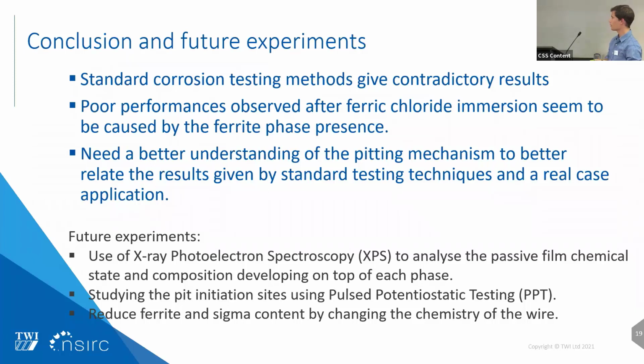So as for future experiments, we'll run some X-ray photoelectron spectroscopy to characterize the passive film that we have on top of each phase. The goal here will be to look at the chemical state of the film and see if we can find any weak points that might be located at the interface between the austenite and the other phases, which are sigma and ferrite.